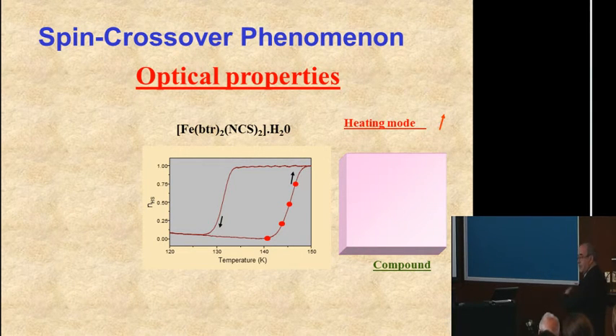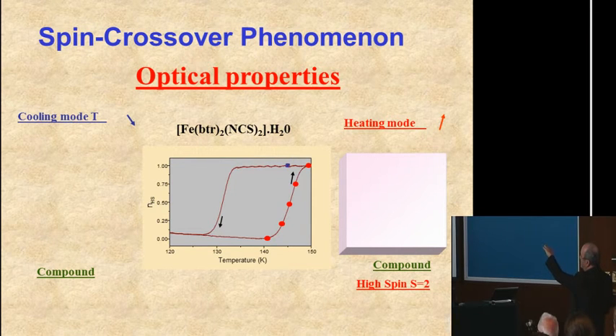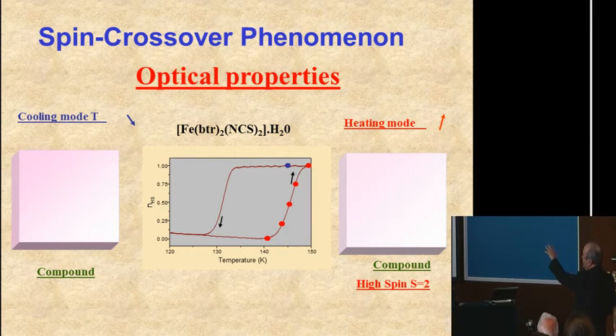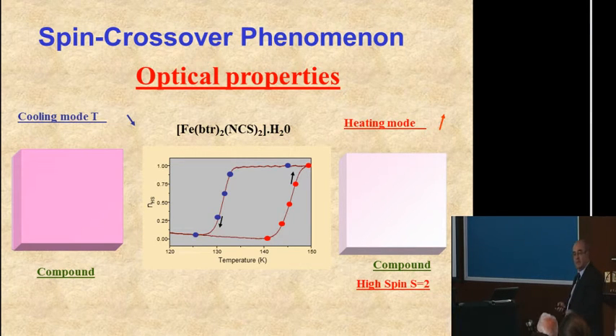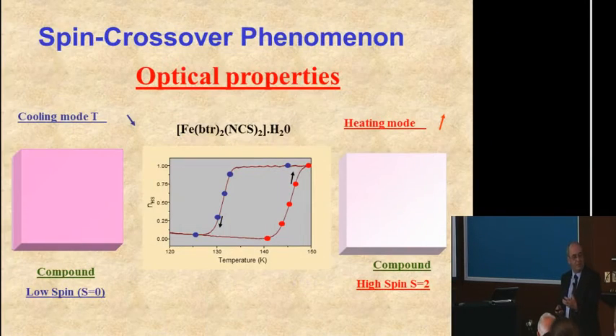So when the system goes to the high spin form, it changes its color from pink to white. And of course, if you come back, I mean you go through the hysteresis loop and you are white, and then when you decrease your temperature, the system will go to the pink color, and then the system is in the low spin form. That means that by just temperature, you can switch the optical properties of your system, and you can see all the applications you can have through these materials.